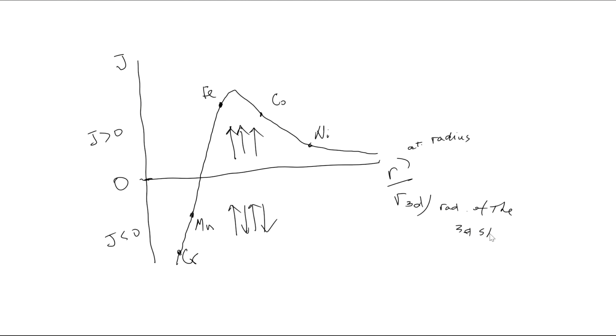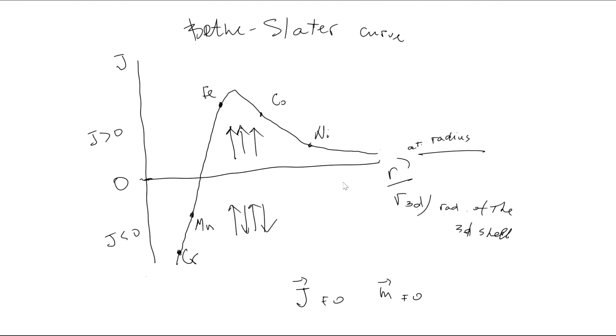Okay, so this curve has a name. It's the Bethe-Slater curve. And looking at it, you can clearly see the interactions, and you can see that iron, cobalt, manganese, and chromium all possess magnetic moments. So they have J non-zero, which means that they have a non-zero magnetic moment. But still, the arrangement of these elements in the crystal lattice, bringing them close together, would define how they interact. And that defines that we'll have very strong interaction for iron, let's say, and chromium, but the type of interaction would be different because they have different atomic radius. And it is the same for other elements.